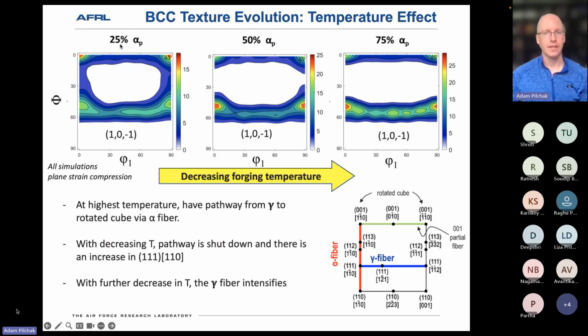So we already looked at the 25% primary alpha case. So now we're going to look at 50% and 75%. It's interesting. It suggests that lower forging temperatures, so having 50% alpha, 50% beta, has the same impact. It shuts off that pathway to get orientations flowing from the gamma fiber up to the rotated cube, and also strengthens that 111 texture component there. And things only get better as you go to lower forging temperatures.